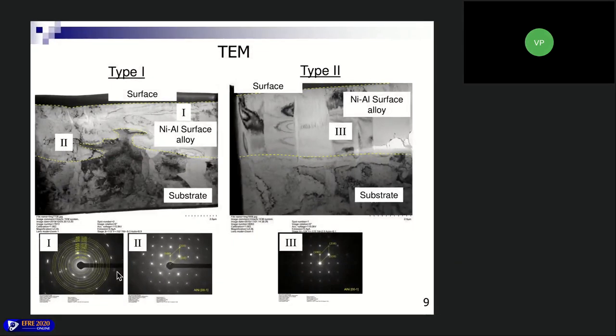So this slide shows us the transmission electron microscopy and the structure, which also corresponds to the nickel-aluminum intermetallic structure. But in the case of the thick layers, we can also see a circular structure, which can correspond to very small particles.